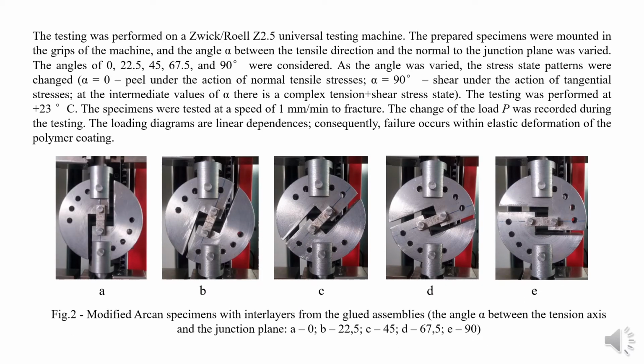The testing was performed on a Zwick Roell universal testing machine. The prepared specimens were mounted in the grips of the machine, and the angle alpha between the tensile direction and the normal to the junction plane was varied. The angles considered in the work are shown in figure 2. As the angle was varied, the stress state patterns were changed.